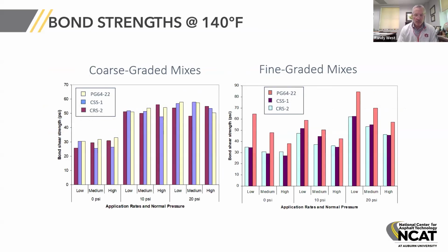I do want to point out a few things. Number one, we saw the effect of the mixed gradation. The coarse mixes were not very sensitive. This is at 140 degrees, so this is a very high temperature range that we worked at. The coarse mixes at 140 degrees were not sensitive to the types of tack, whereas the fine graded mixes were. In fact, the PG 64-22 gave the highest tack. That's the pinkish bars, and that's regardless of the confinement or the normal load, and regardless of the tack coat application rate.